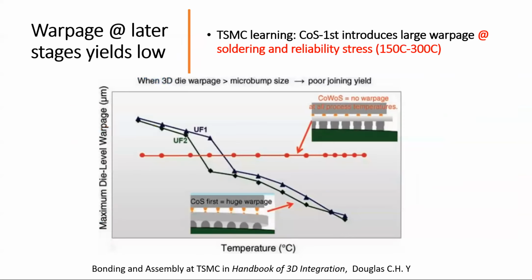I also mentioned last time about TSMC. They have a big warpage issue, especially in this process called the chip-on-substrate-first approach. In this process, the substrate is very thin, and they put a thin die on top. Once they've done that, they find out that there's a huge warpage, eventually causing the yield to be very low. And the warpage happens later in the process. It's not happening right away. The moment you bond them, they're fine.